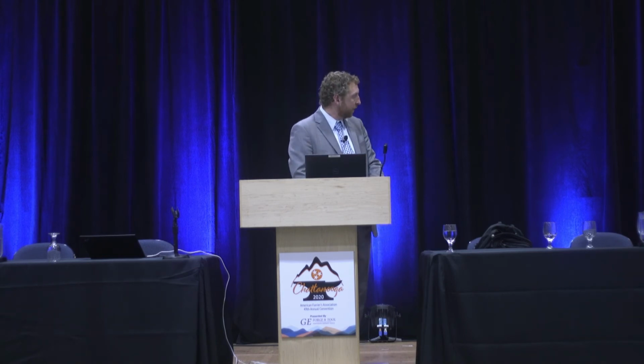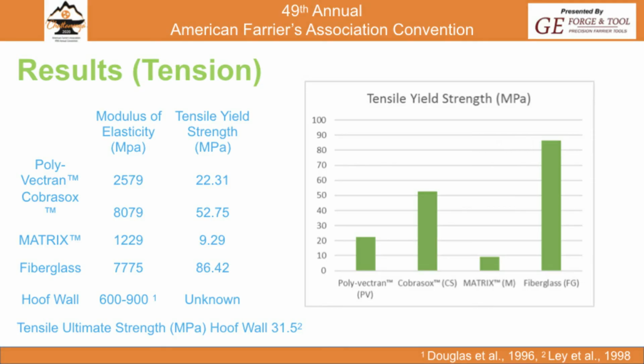Okay? So when we look at them, that's what we tested. So in tension, we tested the modulus of elasticity of those 4 composites. Again, the modulus of elasticity just tells you how stiff it is. So the higher the number is, the more stiff or more rigid it is. And so all of these for the modulus of elasticity are all greater than what is reported for hoof wall. But again, I really think the tensile yield strength is what we should be looking at, and tensile yield strength of the repair composite should be greater than the ultimate strength of hoof wall.